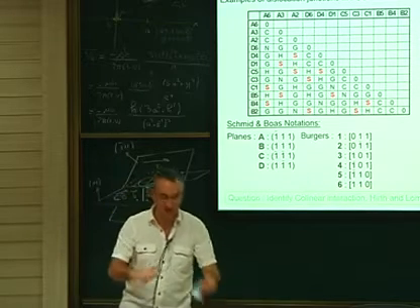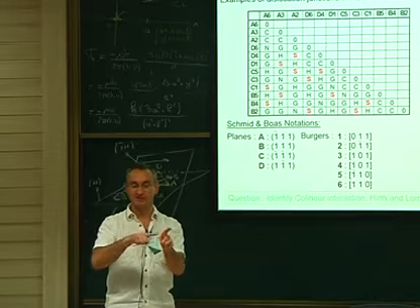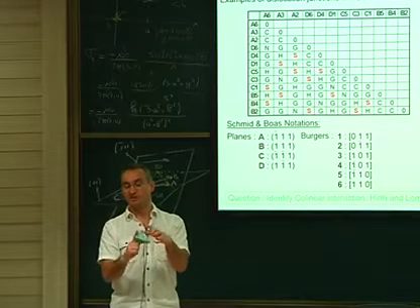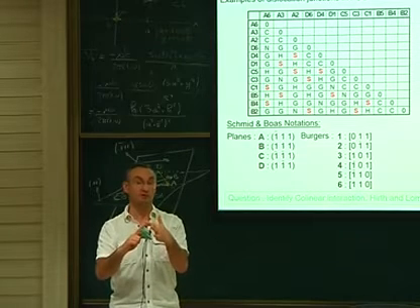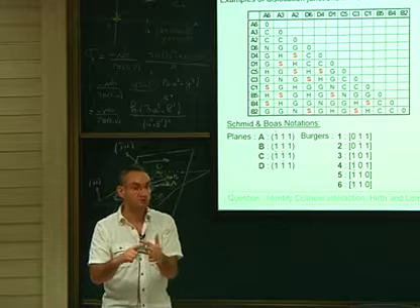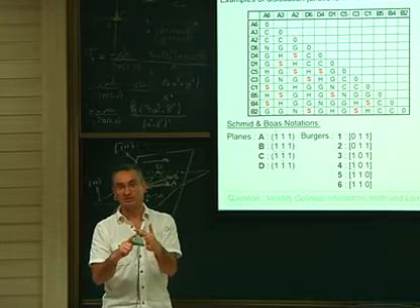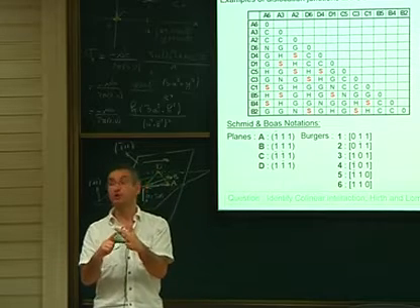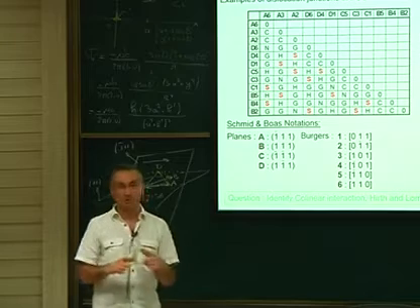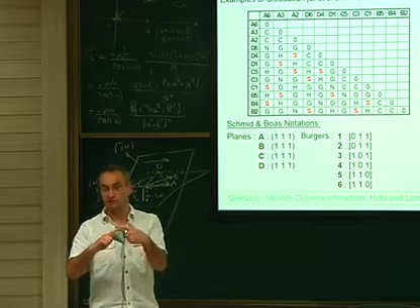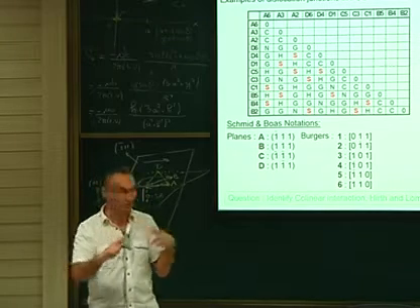Although they are not in the same plane, it means that one is here, one is there, they share this Burgers vector. When they intersect, the junction is 0 Burgers vector. B1 plus minus B1 will give 0. Okay. So that's the last case where you have what we call the collinear junction, C, which is a strong junction actually because there is no junction. It has removed the junction part.